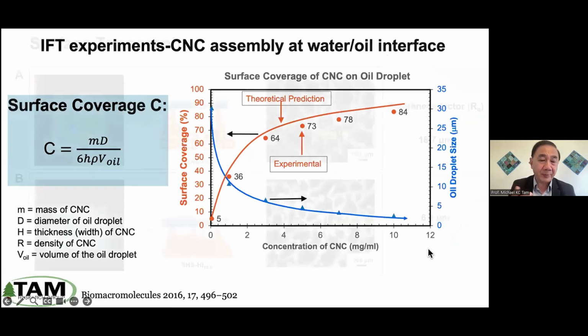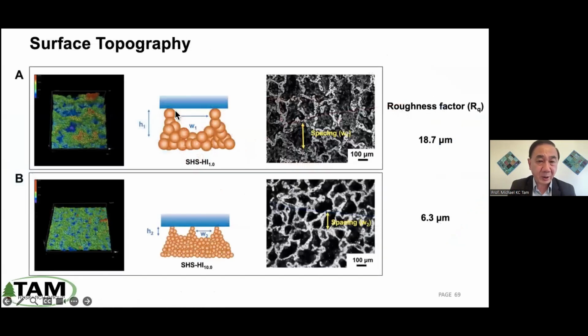So now we want to prepare with spray coating. You can control the height and the width, and that would control the roughness, and that allows us to be able to manipulate the super hydrophobic characteristic and also the adhesion property.